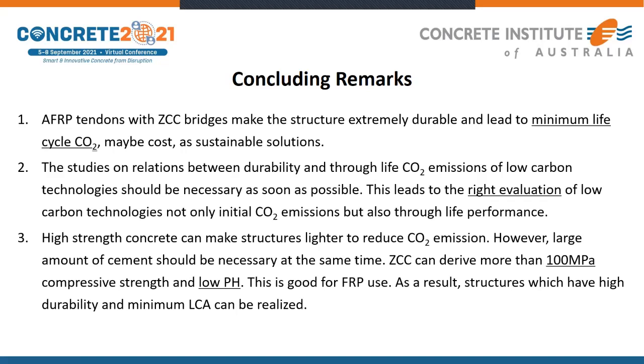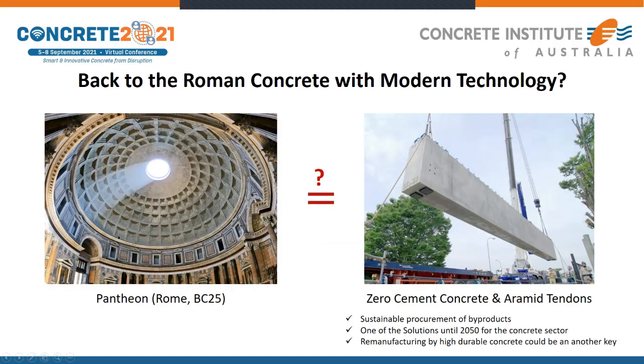High strength concrete can make structures lighter to reduce CO2 emission. However, a large amount of cement is necessary at the same time. Zero cement concrete can deliver more than 100 MPa compressive strength and low pH. This is good for FRP use. As a result, structures which have high durability and minimum LCA can be realized, as I showed in my slides. Finally, we have to go back to the Roman concrete with modern technologies.